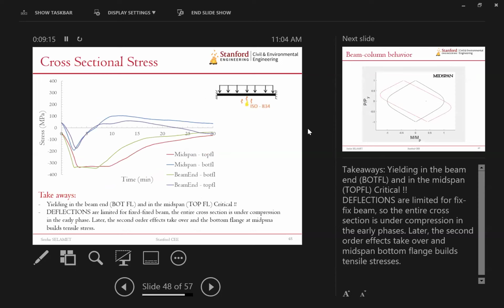When you look at the stresses for a fixed beam, we can look at the stresses at the midspan as well as at the beam end. The takeaway from this would be the yielding in the beam end, bottom flange, and the midspan, top flange, it's critical. And the deflections are limited for a fixed beam, as we have seen before. The entire cross section is under compression in the very early phase. You can see that